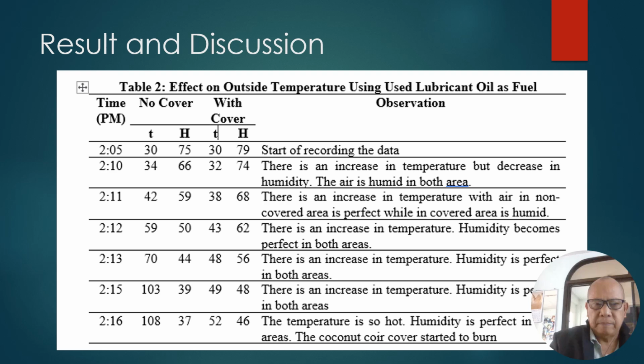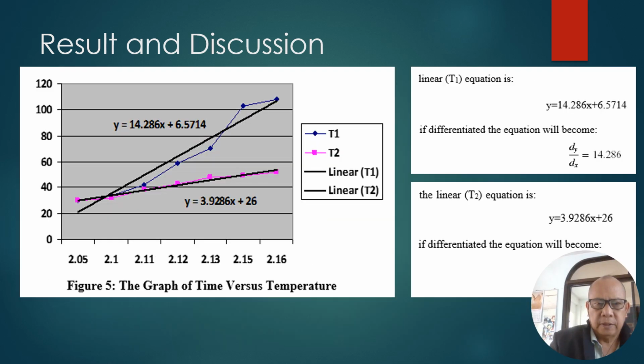At 2:13 p.m., there is an increase in temperature. Humidity is perfect in both areas. At 2:15 p.m., there is an increase in temperature. Humidity is perfect in both areas. At 2:16 p.m., the temperature is so hot that it reaches 108 degrees Celsius. Humidity is perfect in both areas. Then the coconut coir cover started to burn.